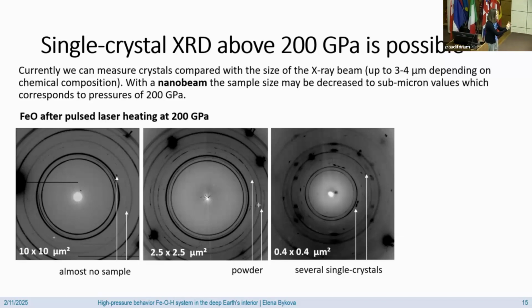If we start to tighten the focusing and decrease the beam size, we start to see 2 weak powder lines, these 2 things here. But from 2 powder lines, again, it's really hard to determine unit cell parameters. You can only approximate and just make some guess. Maybe it's some cubic phase. If you don't have so many peaks, maybe it's a highly symmetrical phase.